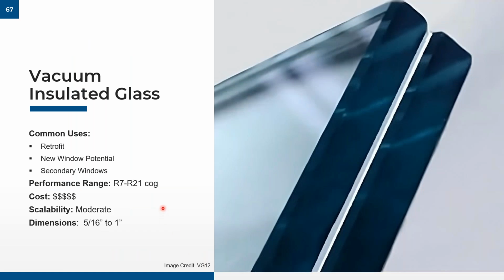So in summary right here, vacuum insulated glass can be used in many different applications, from retrofit to new windows and also secondary windows. We've seen this being used in historic applications as the interior layer to add performance to that historic window. Performance range is very similar. Actually, we can top out a little bit higher than what we saw with thin glass, and starting baseline is about the same. Overall cost is going to be higher than that thin glass that we saw earlier, and these are rapidly scaling up, but we still see these going through that scale-up period today.